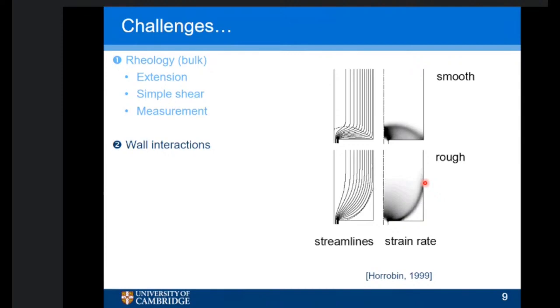These systems are very dense, so the particles will be pushed against the wall. And there, the issue is, can you get something that promotes sliding of the particle along the wall, and also that the coating is hard enough not to be abraded by the particles? With the tungsten carbide system, that's one of the issues, because effectively you are extruding abrasives. That's why we have tungsten carbide tooling, because that's the only thing you can extrude tungsten carbide paste through, and still have an extruder at the end of it. So yes, it's possible, and it really depends on the chemistry and the strength of the coating versus the particles. There's a lot of work to be done here in terms of relative hardness of particles against material and things like that.